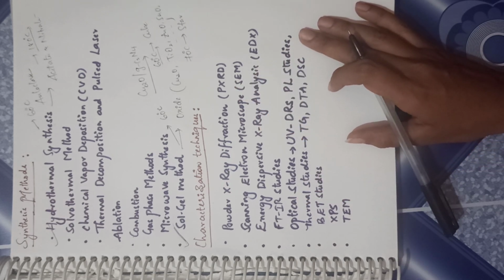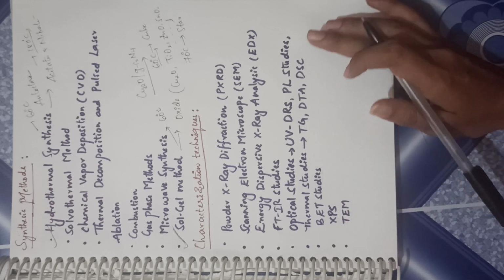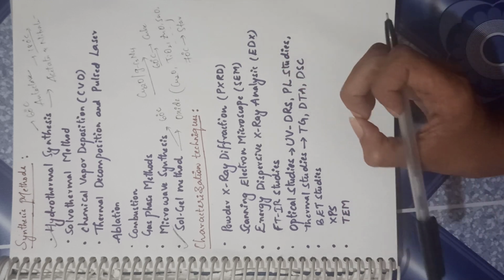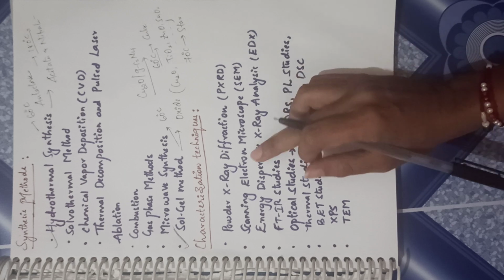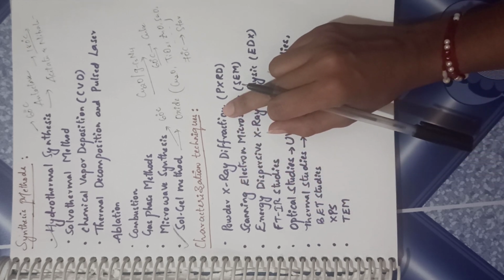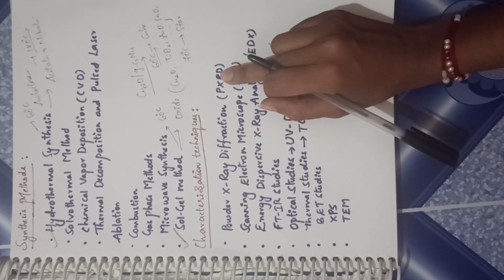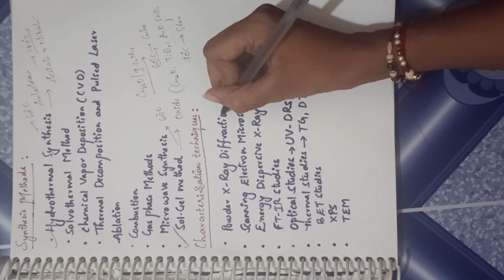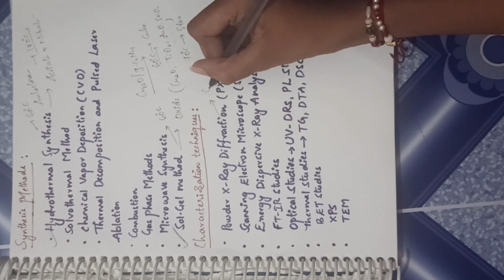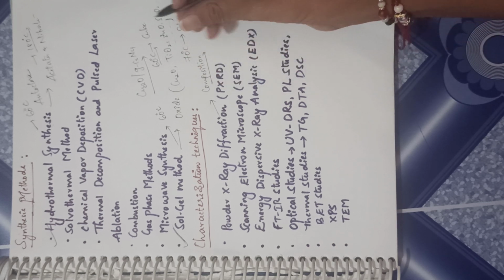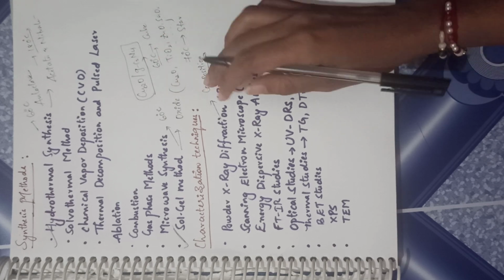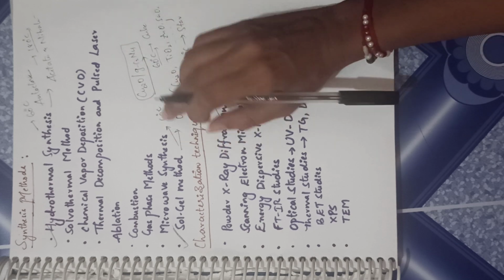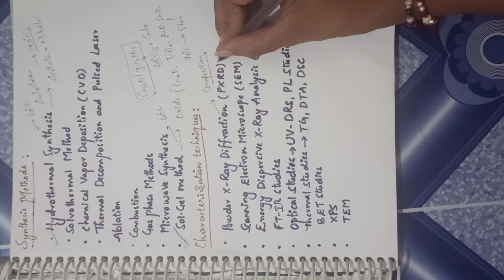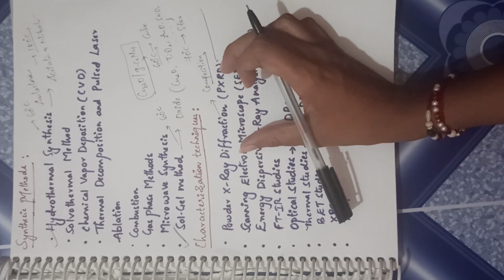So the very first characterization, wherever you are in the world, if you are synthesizing a material, you will go with the powder X-ray diffraction studies, that is PXRD, powder X-ray diffraction. So this is the first confirmation of the composition of the material. If your material is formed or not. I wanted to synthesize Cu2O, g-C3N4. Was I able to synthesize it? Is it formed or not? The peaks of Cu2O, the peaks of g-C3N4 in the XRD confirms the formation of the material.